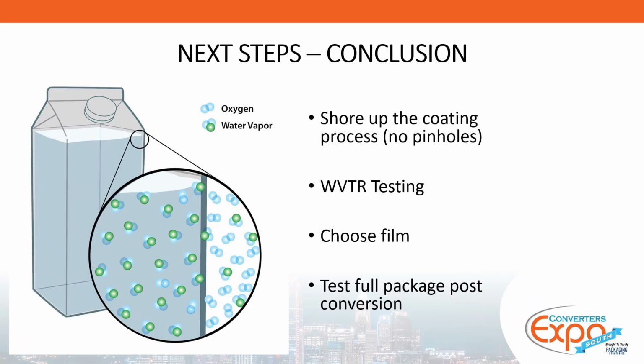So they shored up the coating process, did more water vapor transmission rate testing, found the best film and coating combination. Then they converted into a carton and they tested the whole carton because a package is a system. And once it's converted into this carton here, you have seams, you have closures. These things are potential leak points. So you really have to test the whole system and make sure that these leak points have the barrier that they need, because it doesn't matter how high your barrier structure is if after conversion, you have leaky seams